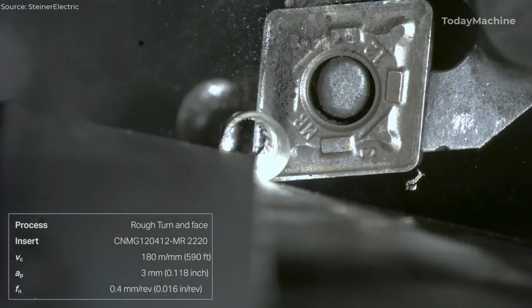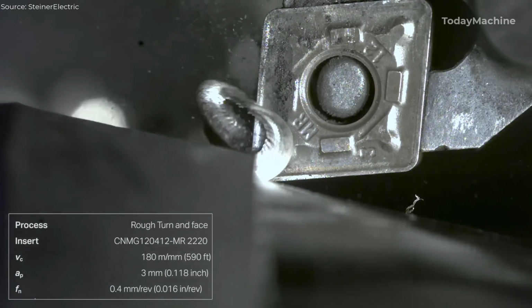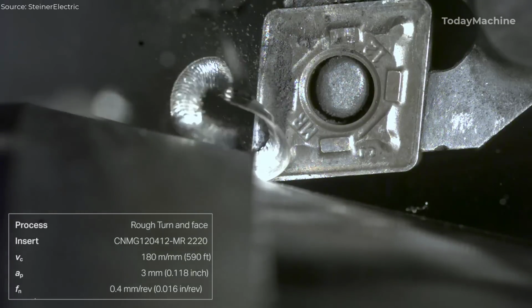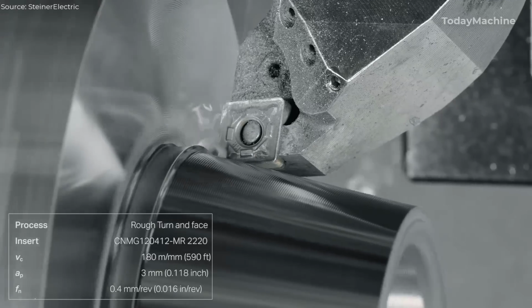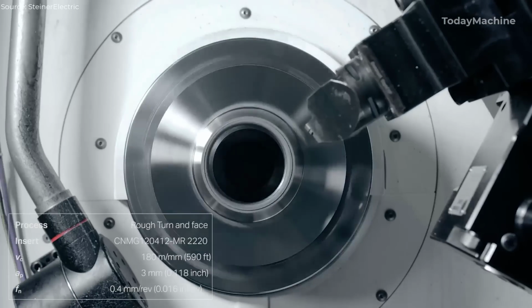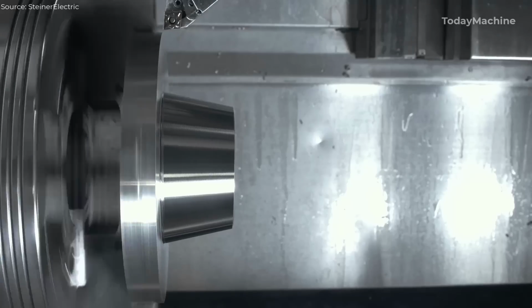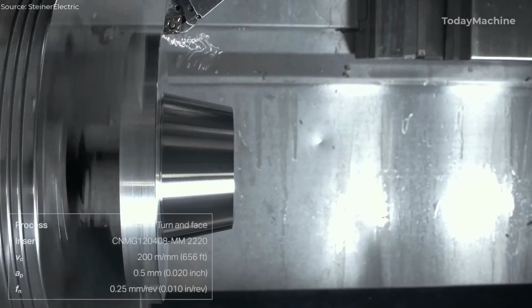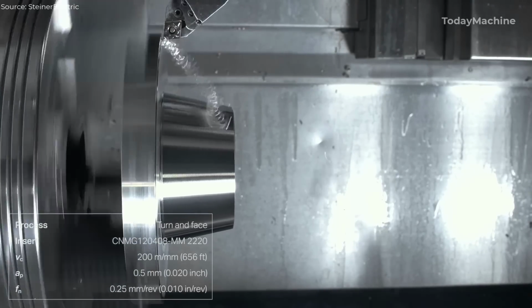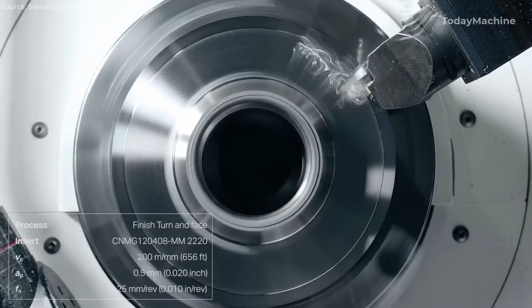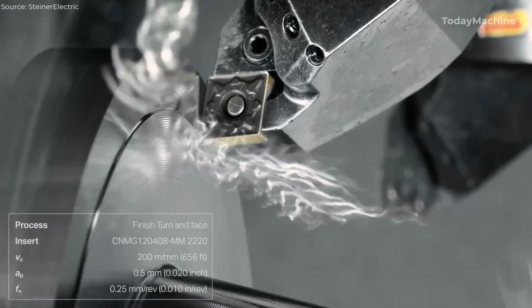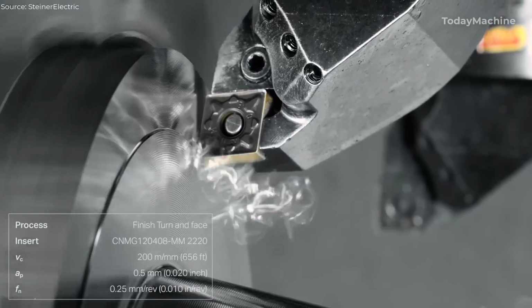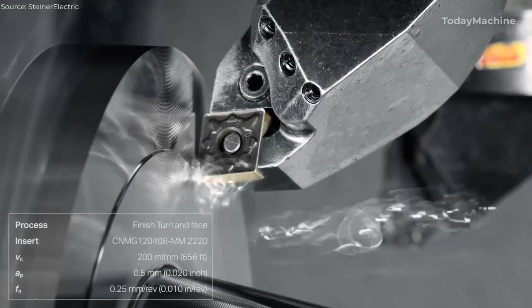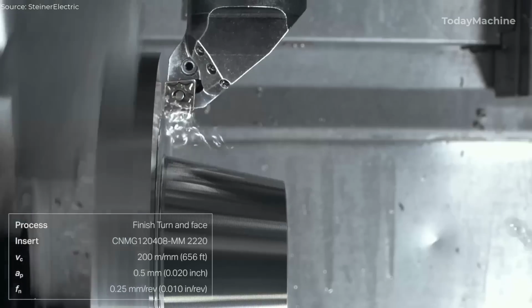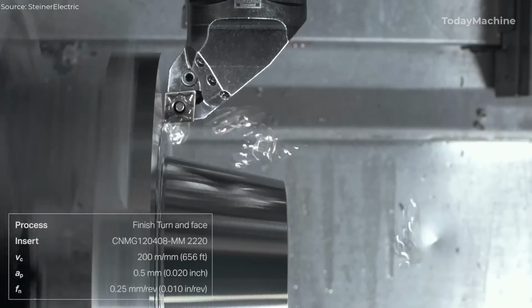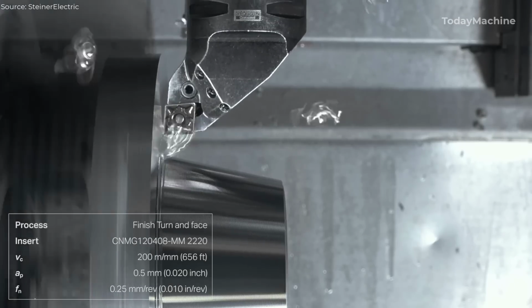A key feature of the GC 2220 is the Inveio coating, which enhances wear resistance and extends tool life. The coating consists of tightly packed, unidirectional crystals that form a robust barrier between the cutting zone and the chip. This barrier significantly reduces the amount of heat generated at the cutting zone, leading to improved crater and flank wear resistance. As a result, machinists can expect longer and more predictable tool life, which is especially important when working with materials like austenitic and duplex stainless steel.